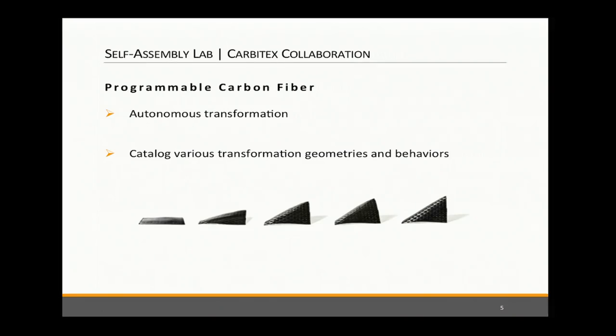So just to touch quickly upon the work that was a phase 1 in collaboration with the Self-Assembly Lab, where we tuned carbon fiber in terms of just the stiffness and flexibility. And Skylar and Athena at the Self-Assembly Lab were able to print a heat-activated polymer system onto our carbon in various patterns and orientations in order to induce a very predictable and controllable change in the material.